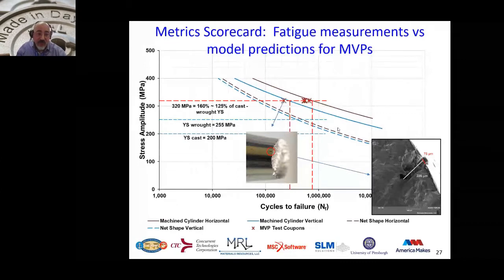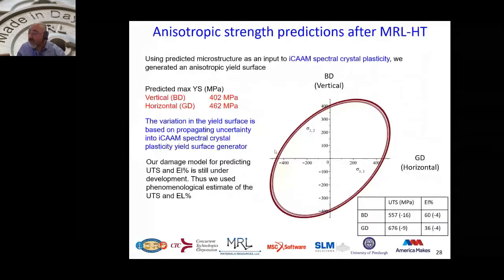And then one of the tests that was done by CTC had one of the samples resulting in something totally out of the repeatability. So you can see the spots here showing you the repeatability. Then we have one sample that was an outlier. In a blind test, we predicted that this sample had an anomaly on the surface because it met closer to our surface defects than our machined surface. And when we got it, we discovered that, in fact, the sample did not pass initial inspection, and it did indeed have surface defects, which we are confirming here. And that was another unintentional blind test. The prediction for the anisotropic yield surface, as we showed earlier, was within about 5% of the experimental measurements.